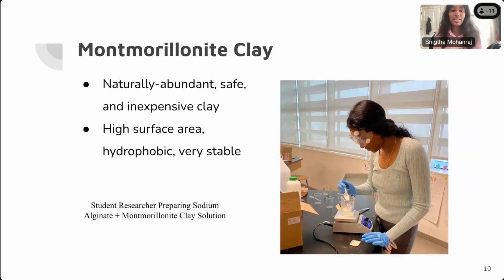So montmorillonite clay is a naturally abundant, safe, and inexpensive clay. It also has a very high surface area and is stable, and it can add hydrophobic properties to the sodium alginate, which is hydrophilic and not as ideal for water contaminant removal. So it's essential to be using montmorillonite clay in addition.